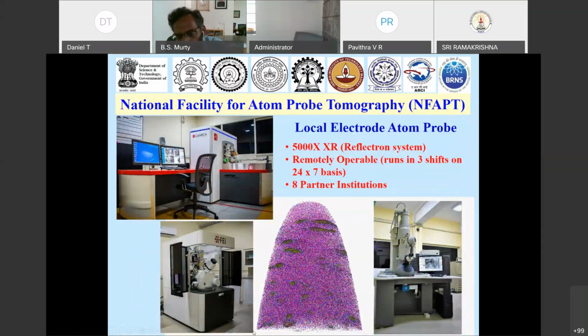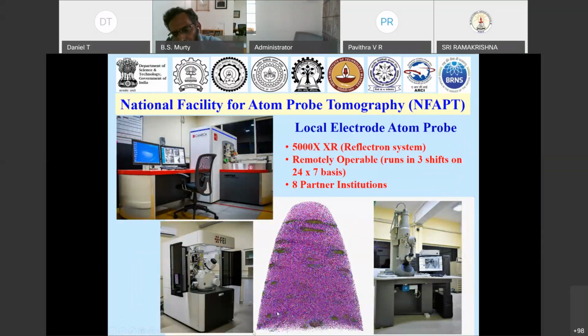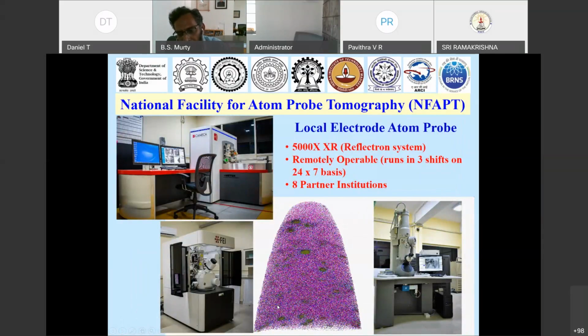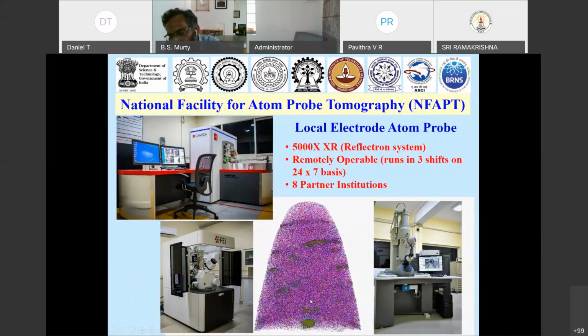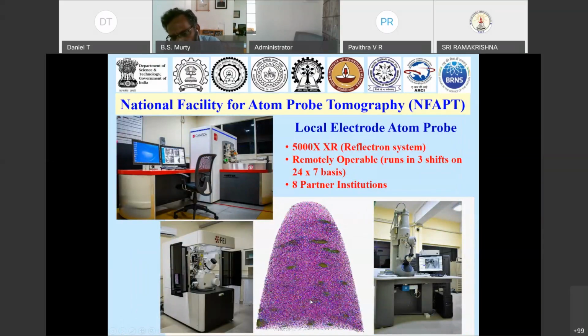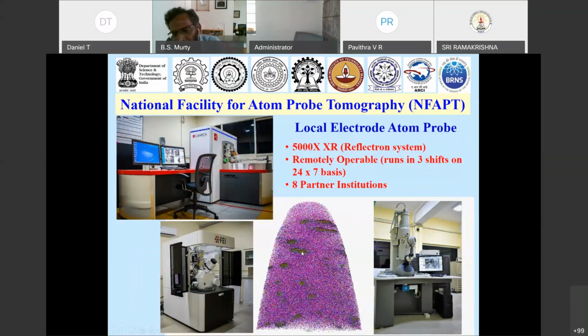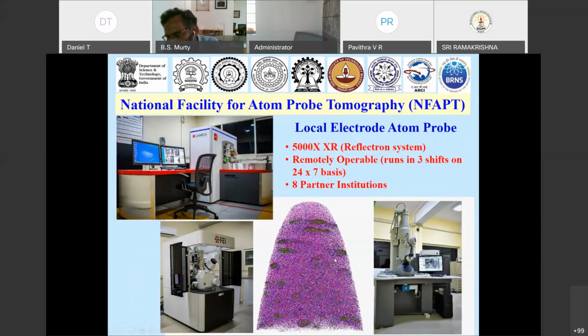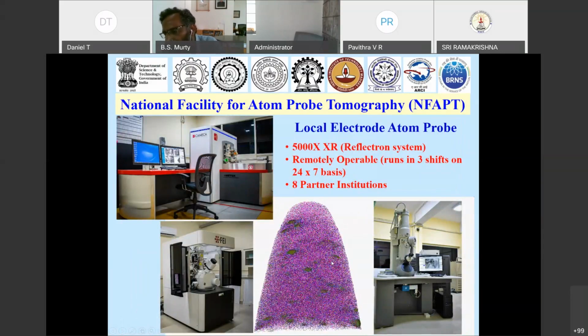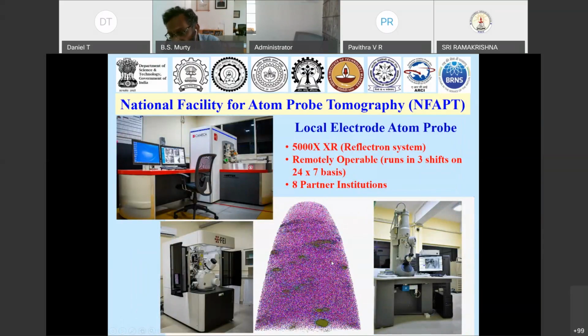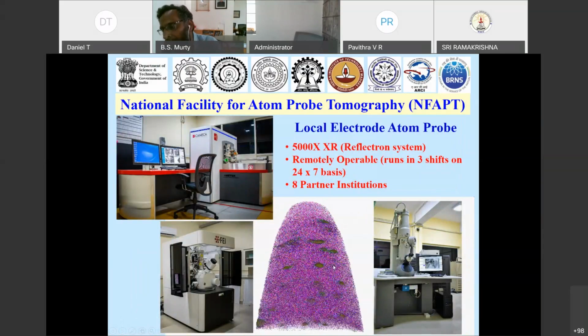With that, if you look at our atom probe, you can see this particular pink sample in the middle. Every pink dot is an iron atom, and inside you are able to see some green color patches. These are all extremely small particles. The size of each particle is about 2 nanometers or so, and inside that you have yttrium, titanium, and oxygen.